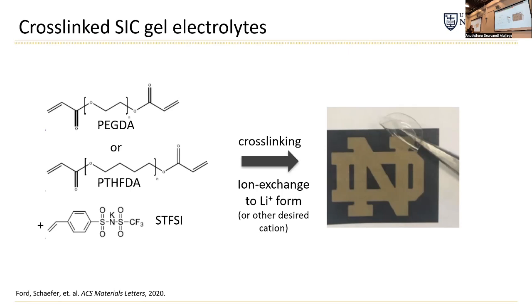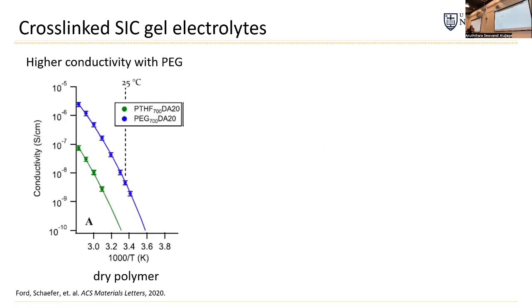So then he brought me this data. The first data he collected was when he had these cross-linked ionomers in the dry form. And he got what you would totally expect from literature, which is that the conductivity of the cross-linked ionomer with the PEG is higher than that with the poly-THF. And that's easily understood because with PEG, the density of its oxygens is really ideal for lithium cation solvation. So this should be true.